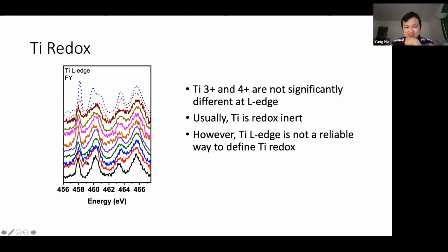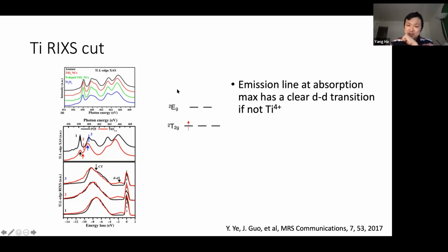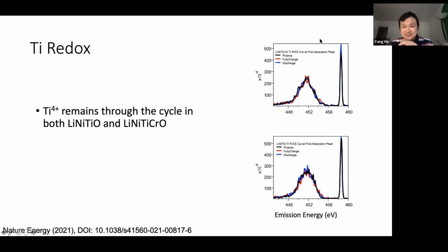So we can see that from the data collected by my collaborators. I have to say, sorry, these are very useless because you really can't tell the difference here. But the good part is for titanium 4+, you have a d0 configuration. And any reduced form of the titanium, you will have electrons in the d orbital. And if we set a particular excitation energy and measure the resonant emission, for any non-titanium 4+ species, we have the band which comes from the dd transition. So this is like bread and butter. Once you see this dd band, you know it's not titanium 4+, and if not, you are sure it is titanium 4+. And in this example, in the 2 sets of materials I measured, I see both remain titanium 4+ through the whole cycles in both sets.